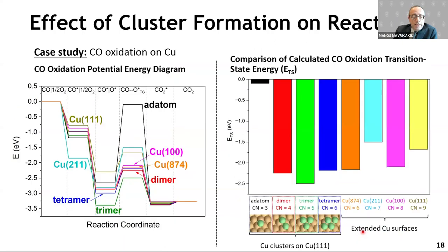So the question then is, how is the reactivity of these novel active sites, the ejected atoms and the clusters you form from them, compared to the reactivity of standard sites that people have been thinking about so far for understanding heterogeneous catalysis or electrocatalysis? In this particular case, we took a very simple reaction, CO oxidation on copper, and we drew here, using density functional theory, the potential energy surface. Here are the reactants, adsorbed CO and adsorbed oxygen. Now this is the transition state to get to the product of the reaction, CO2.